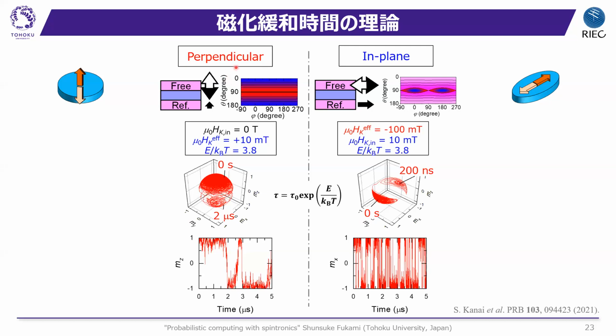But the perpendicular easy axis system is uniaxial, whereas the in-plane easy axis has three different axes with different energies. So for the in-plane magnet, if you'd like to rotate your magnetization in this XY plane, you need to apply 10 millitesla. But if you'd like to rotate your magnetization out of the plane, you need to apply 100 millitesla. So this is not uniaxial, but the three axes are different from each other. And these are the calculated random telegraph noise. So the fluctuation speeds are largely different between these cases, although the thermal stability factors are exactly the same.